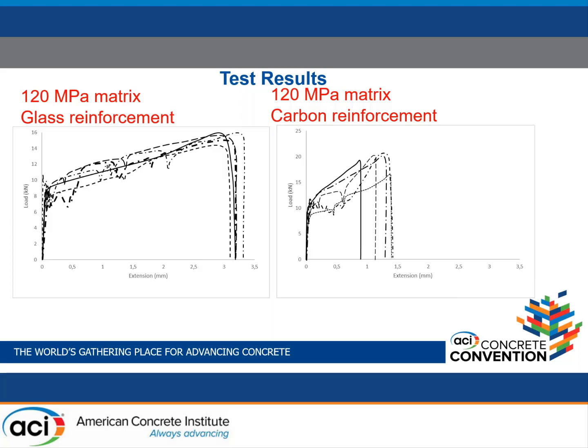These are the test results of 120 megapascal UHPC matrix composite. This is for the comparison of glass fabric reinforcement and carbon reinforcement. However, glass fabric reinforced composites showed higher extension than the carbon fabric ones.